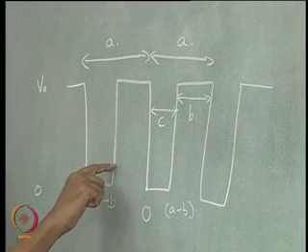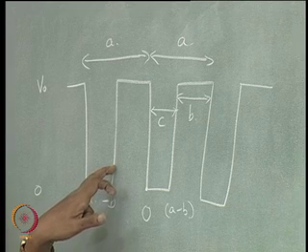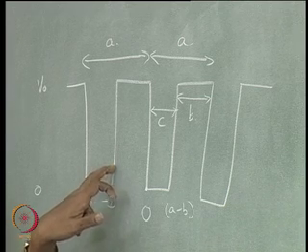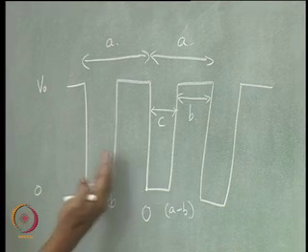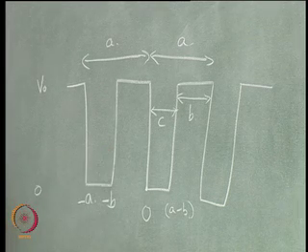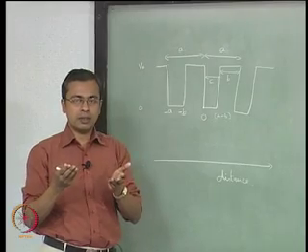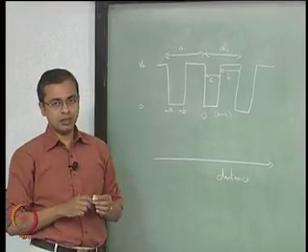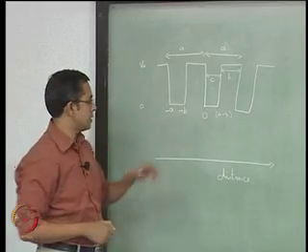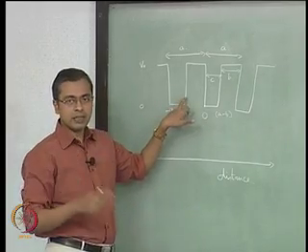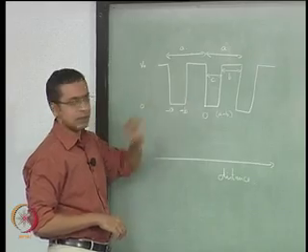So in terms of the value and the slope at the boundary, whether the function is coming from the V naught side or the V equal to 0 side, the value should work out to be the same, and the slope, or the derivative, of those functions should work out to be the same. That will give us two equations for this system.